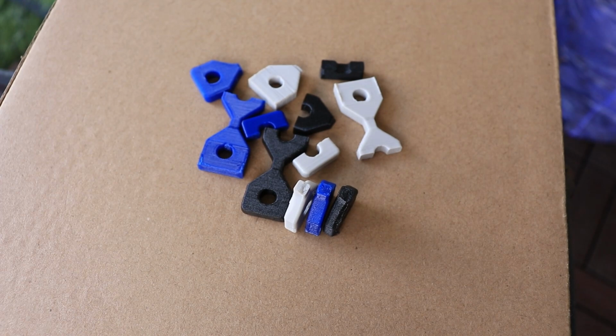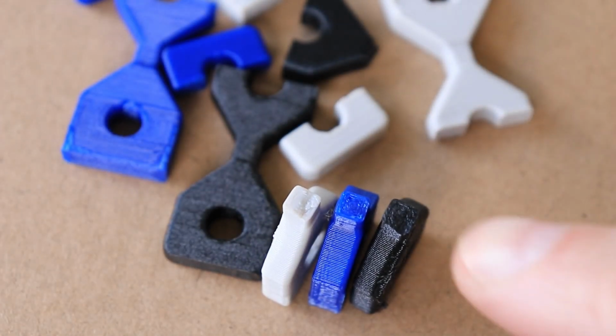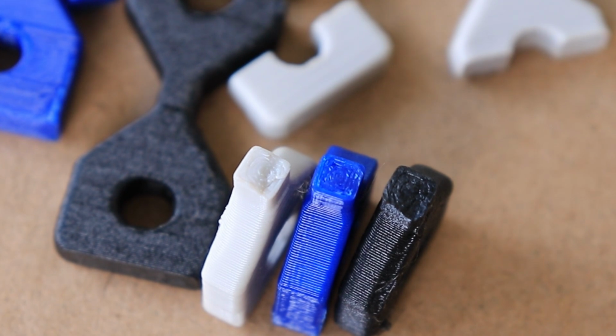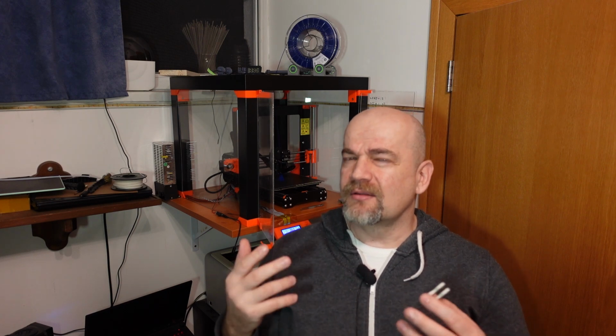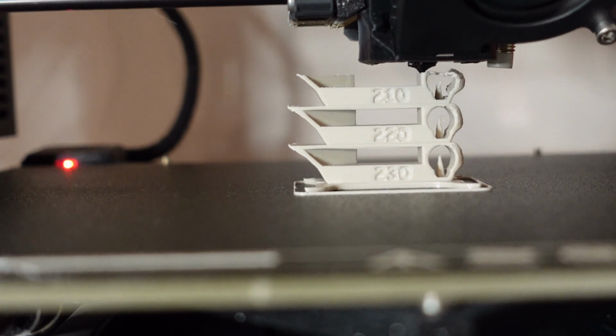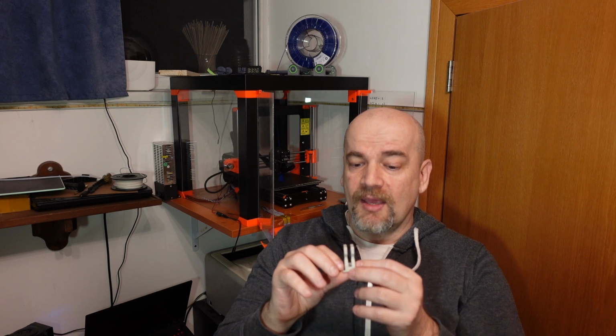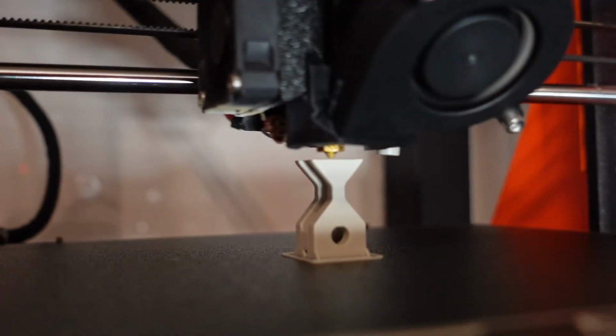They didn't even break equally, but the cross-section area looks very solid in all 3 cases. I think I need a little bit more testing with this. I need one more test for my curiosity, because all test objects were printed using a hardened steel nozzle, and I have that feeling that here the layer adhesion is much weaker. You saw on that PETG temperature tower at 210 degrees Celsius even part of the object broke down because of the weaker layer adhesion. And I'm curious now, since I changed to the brass nozzle anyway because of that clog with carbon filament, I'm reprinting these test objects for layer adhesion.